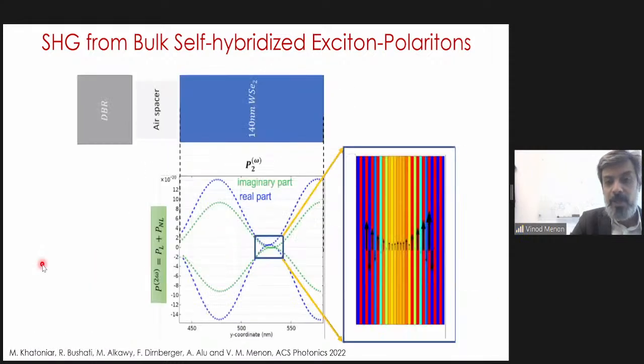So to understand what's going on, we should look at the electromagnetic field. And nonlinear optics is all about phase space, phase matching and so on. And it turns out that within this thick material, 140 nanometers, there is a small region where the polarization created in each layer is not cancelled by the next layer. So in every other layer, it's usually cancelled. One points up, the other one points down. But there are a few layers here where this condition is not satisfied, and where you get net or effectively some nonlinear response. So although the material is 140 nanometers, the actual nonlinear response is coming from a bulk of the material which is sitting inside, which is only about 30 nanometers.